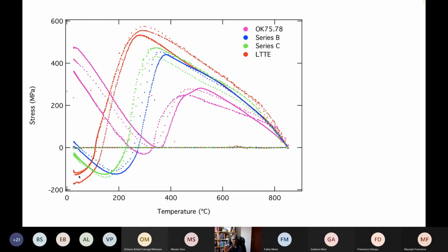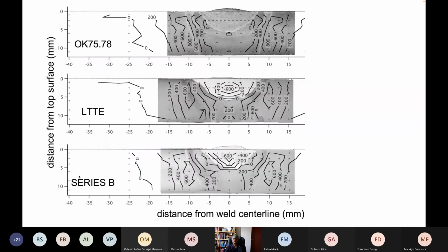Now, of course, these are tensile specimens, and what you've got to do is prove this for an actual weld metal. And these tensile specimens are roughly 5 millimeters in diameter, because the X-rays can then penetrate the whole of the specimen. Whereas a weld will be a much larger object, which cannot be penetrated by X-rays. So we went to Chalk River in Canada to make measurements of residual stress inside actual welds. And these are the results.